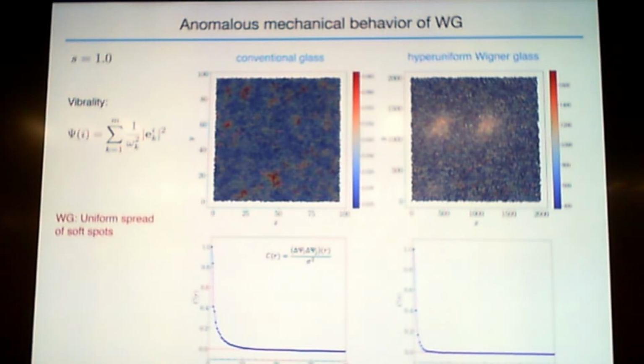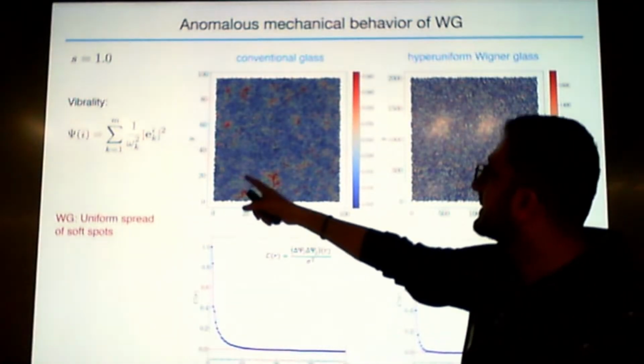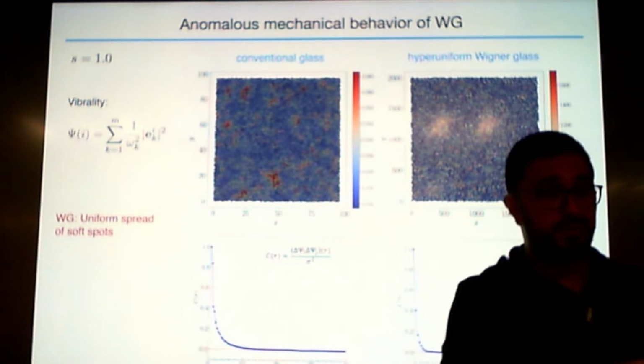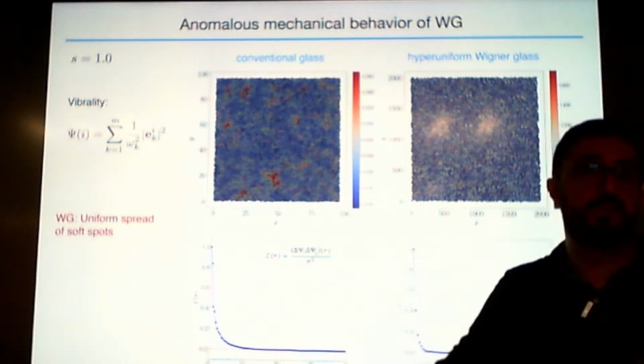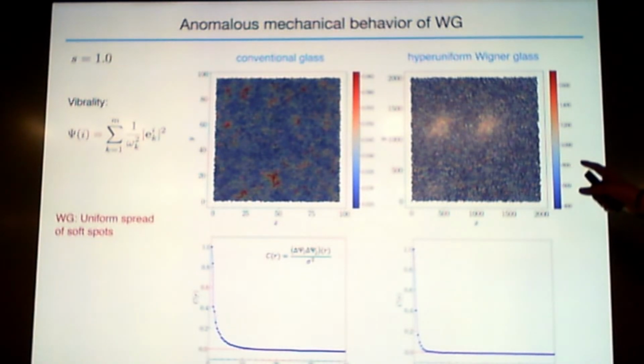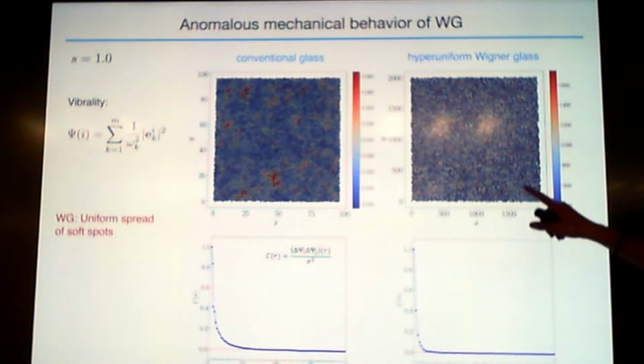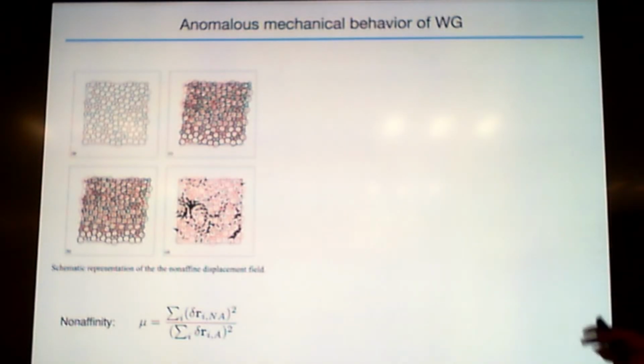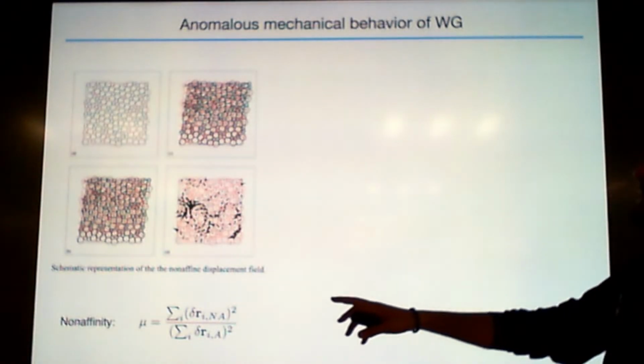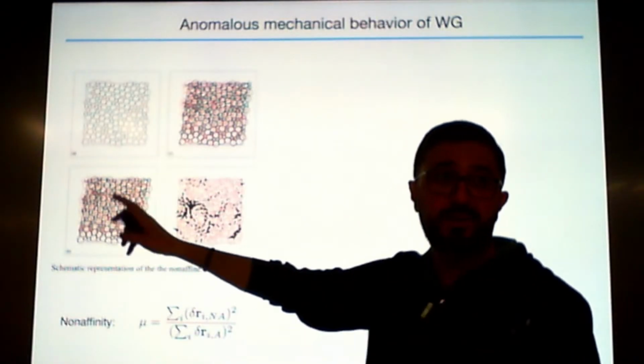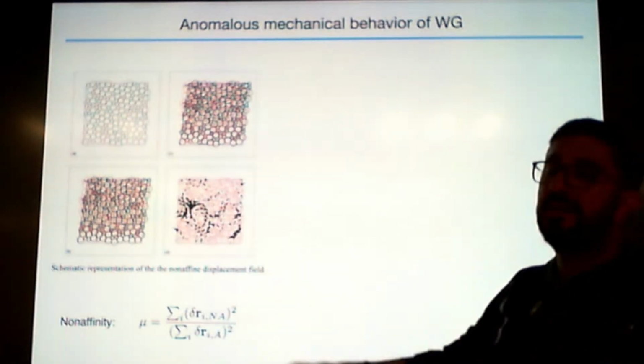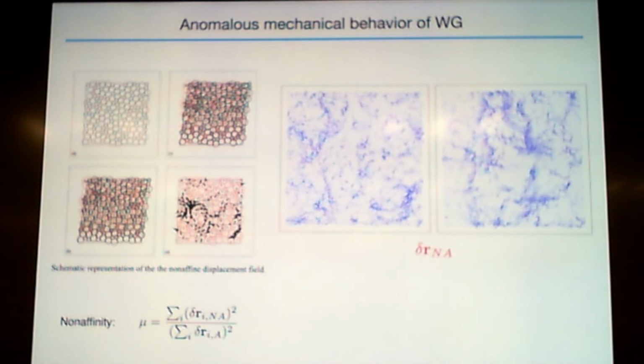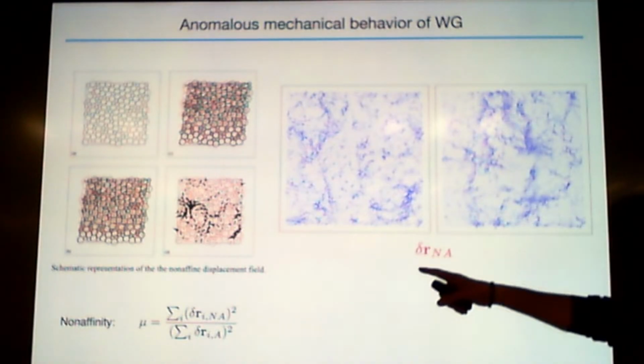Soft spots, because they are more susceptible, more prone to external excitation. For example, when you thermally excite the system, the glass will start fluctuating more in these spots, rearranging more. Here the rearrangements will be higher than in the blue zones. Now if you look at the hyperuniform glass, our glass, it looks fantastically different, I would say. These soft spots are highly localized, point-wise, unlike in conventional glasses. And this leads to the non-affine displacement: you have a glass, you shear it, you get this, you let it relax, you get this, you subtract these two, and you get the non-affine part. This non-affine part is at least 1 order of magnitude smaller in our glasses than in conventional glasses.